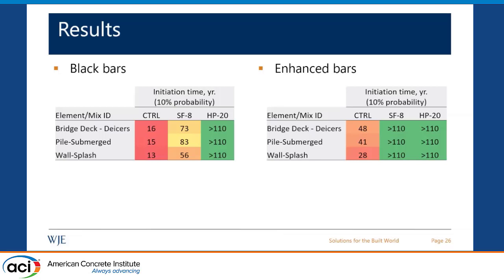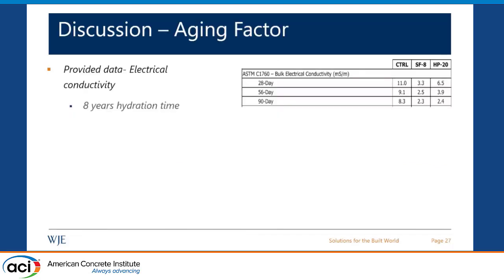And based on that, similar to what others have presented earlier, the black bar didn't give us 100 years of target service life. For the cases with the control mix or the silica fume mix, and for the enhanced bar, the control mix also didn't give us 100 years, but silica fume mixes and natural pozzolan got us to the 100 years. However, if we are modeling this for a project, we might have approached some of these input parameters differently. So, for example, looking at the bridge deck, the Deicer case here, let's look closer at the aging factor.